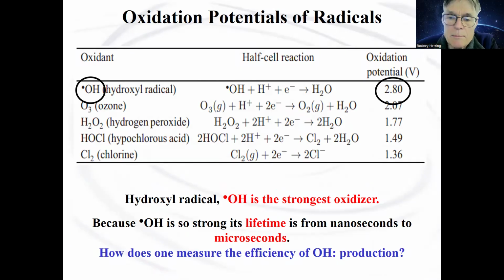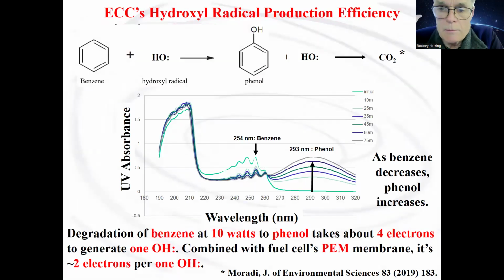So one may ask, how can you actually measure the production of hydroxyl radicals when it disappears so quickly? Well, here's a nice method. We tried many methods, but eventually I came up with this method where we put benzene into some water and we put the reactor generating hydroxyl radicals, and it produces phenol. Both benzene and phenol are very easy to measure using a UV spectrometer. Eventually, all the hydroxyl radicals will degrade this to carbon dioxide. So we can see here in this UV absorption spectrum that initially we have a concentration of benzene. Hydroxyl radicals are being generated, so its concentration is decreasing. We can see that it's producing phenol. So we start with zero amount of phenol, and then over time, the phenol increases. So this enables us to measure the efficiency of generating hydroxyl radicals.